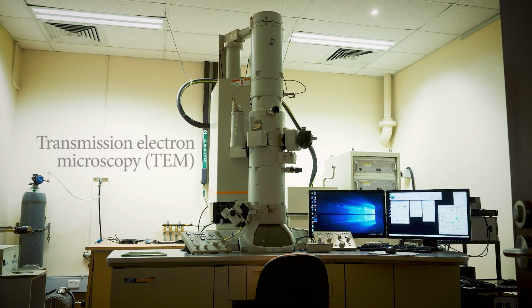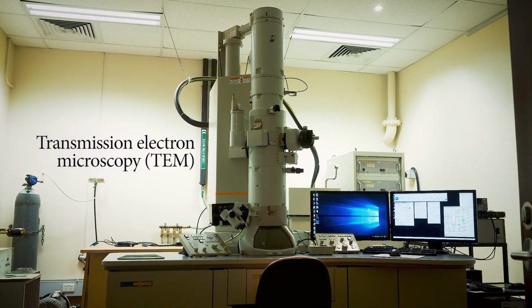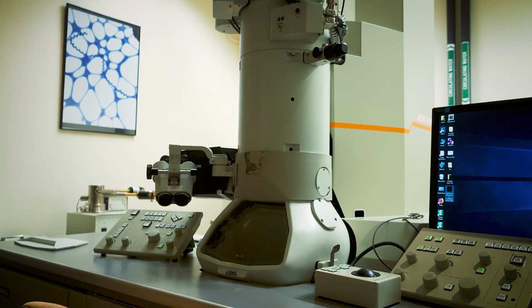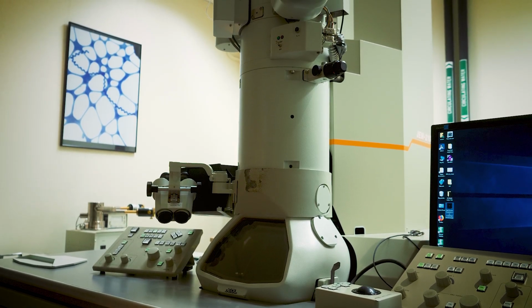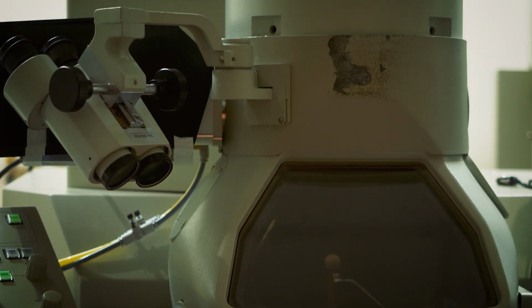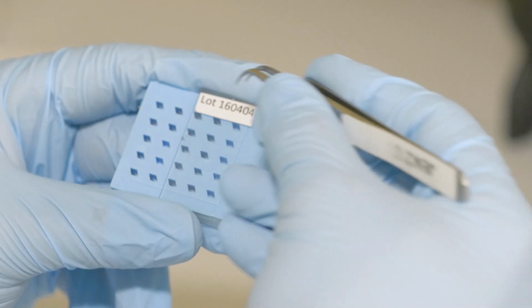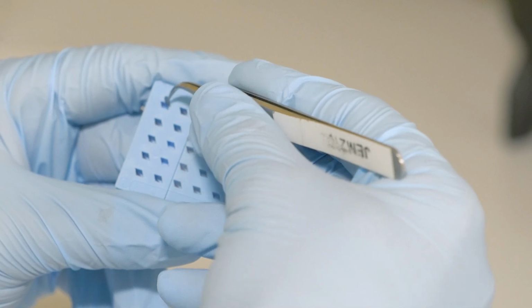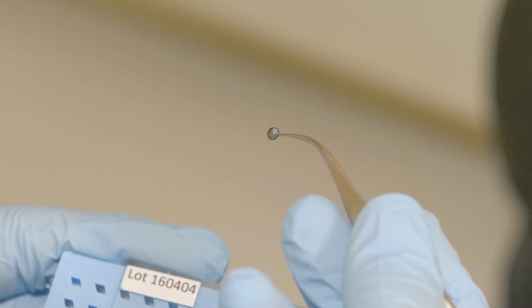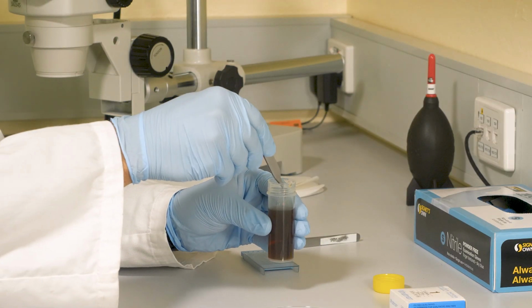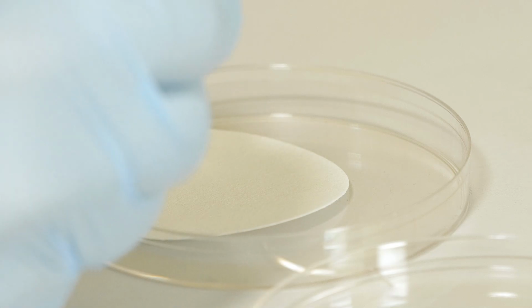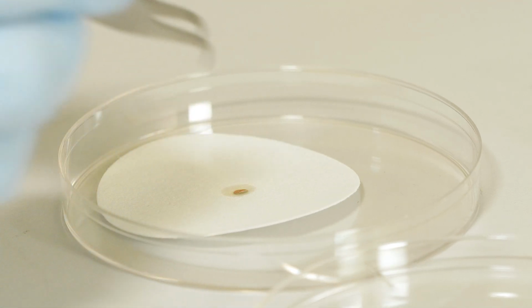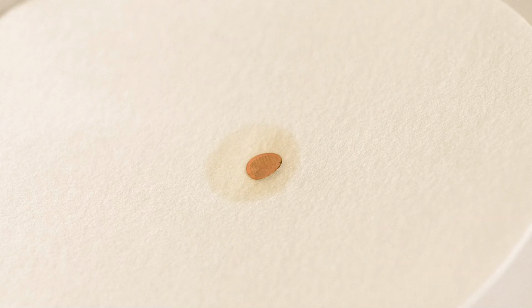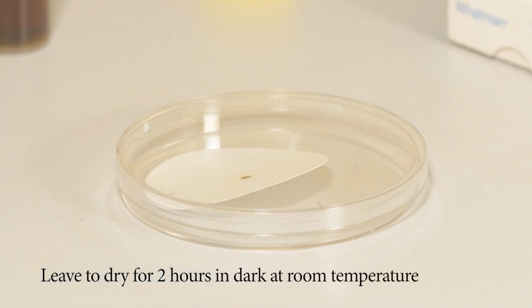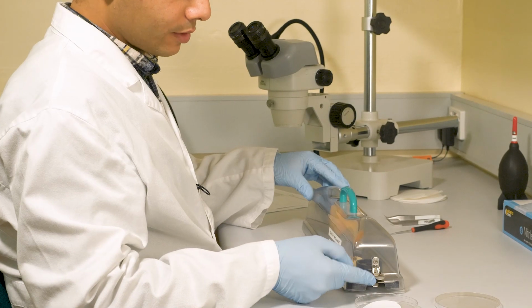I'm going to use transmission electron microscopy or TEM as a super powerful instrument to measure the particle size of my carbon quantum dots. TEM is a microscopy technique in which a beam of electron is transmitted through a specimen to form an image. First, we prepare the TEM grids by dipping the grid into the synthesized carbon quantum dot solution. We will leave it to dry for a couple of hours in the dark and room temperature. Now we have our sample ready.